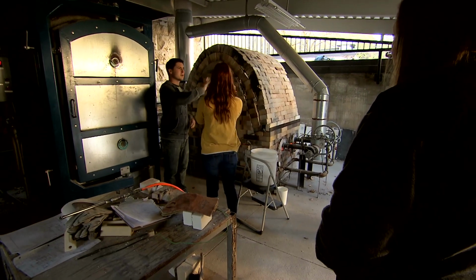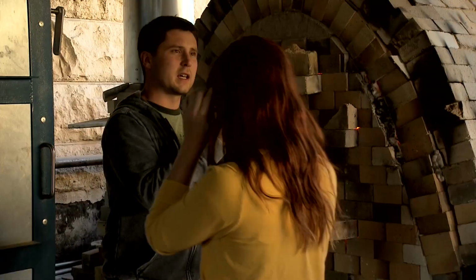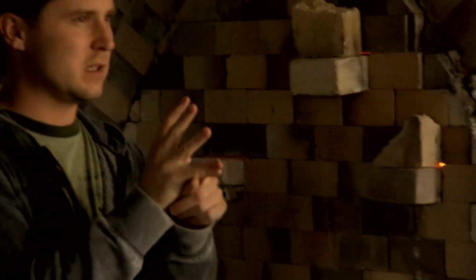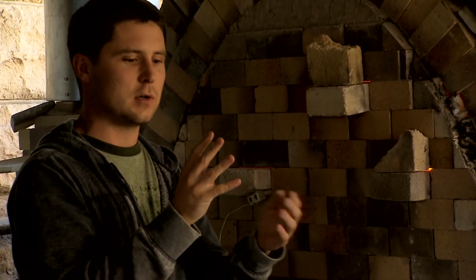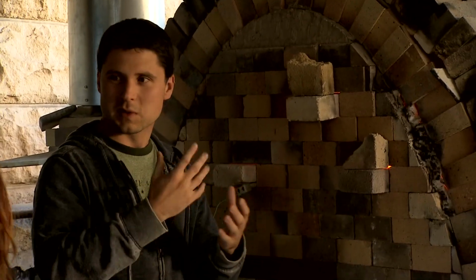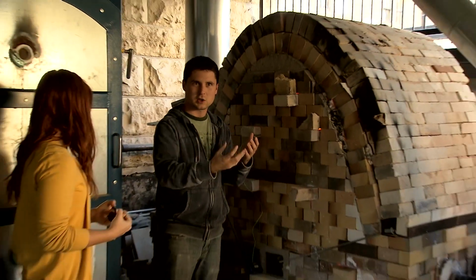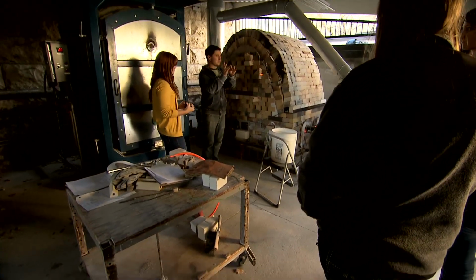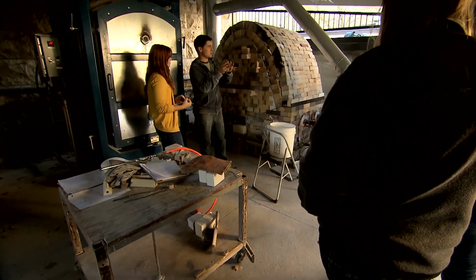So those cones, I had 4 of them. We did an 010. That melts really low, even before the 04 that you guys glaze your sculpture to. 010 melts, and that's when you start your reduction. That's when the clay body can still absorb the carbon from the reduction and pull out the color from the glazes. And then you'll see cone 5, cone 6, and then cone 7.